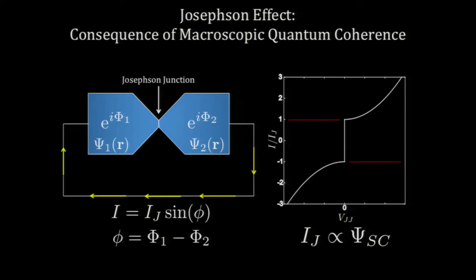And the maximal current that can flow is set by this I sub J, which we call the Josephson critical current. So you see here, for example, if I put a current source here and try to push current through the system, no voltage will appear across this junction. So here's the current increasing, no voltage across the junction until you hit the critical current, and then you become normal. And then you go on to your normal branches. And by measuring that critical current, you actually have a measure of the superfluid density, or a measure of the condensate order parameter.